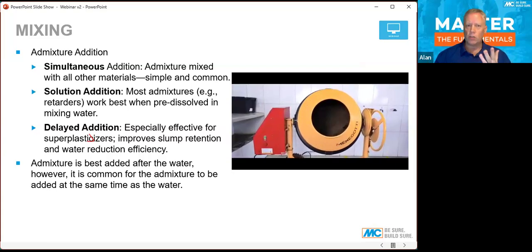There is a second one, solution addition, which is when on a batching plant, the admixture is pre-dissolved in the weighing water and then put into the mixer. Now, the third one, and the most effective one, is not commonly used. So it's after all the other materials are in the mixer and mixed, including the water, then we add the admixture. And when we do that, we get better performance from the admixture. It improves the slump retention and the water reduction efficiency. So the best time to add an admixture in the mixing process is last.